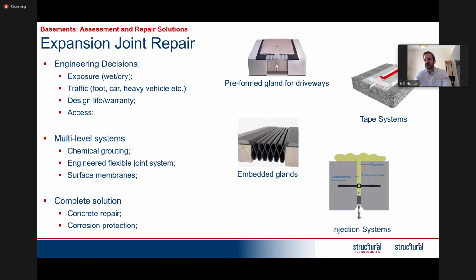Or you can have other gland systems which are actually embedded into the concrete. They're embedded either side of the joint, and they'd be secured down with a cementitious material. Or where you have groundwater involved, normally you would require some kind of injection. This could be, like we discussed before, chemical grouting of the joint itself. It could be chemical grouting of the soil behind the joint. It could be a combination of both, and the complete system could be a combination of injection plus some kind of gland plus a tape system on the top, depending on how many lines of defense you require, and also depending on the specific site conditions.